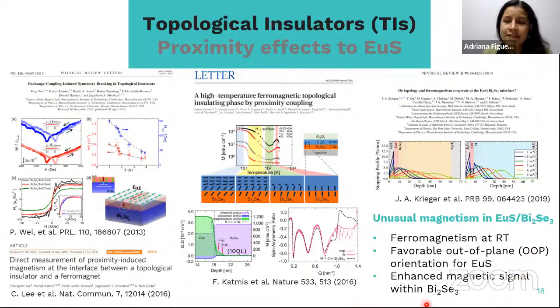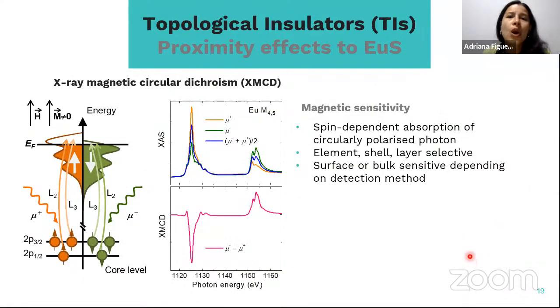And in this case, we used a very advanced characterization technique that allows us to have magnetic sensitivity in a very selective way, which we call X-ray magnetic circular dichroism. This is a technique that is performed at synchrotron radiation facilities and is based on X-ray absorption spectroscopy and the transitions from core level electrons to the continuum. It provides very relevant information about element, shell, and layer selective magnetometry.